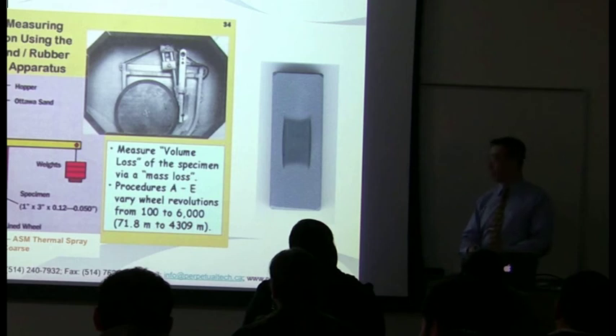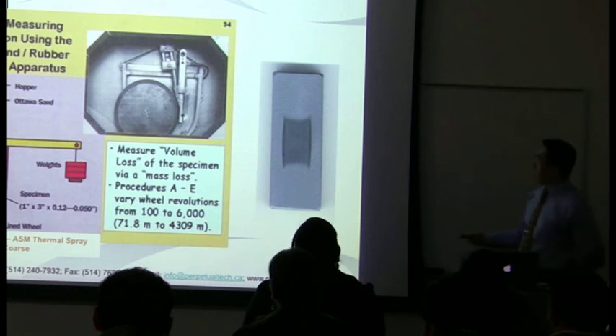Because that's really what we're concerned about. And you can see here, this is a photograph of our sample after exposure to this wear test. Here's the wear scar.